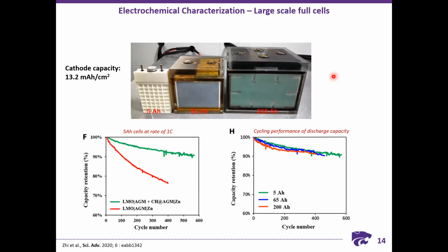They have also gone one more step to produce large scale full cells with the 5Ah, 65Ah, 200Ah batteries for the zinc metal batteries. So for zinc metal batteries, they have used aqueous solution of a combination of zinc sulfate and lithium sulfate electrolyte. So for zinc metal batteries alone, they have made large scale full cells of these capacities. So even when they move to commercial level scales, you can see the capacity retention they were able to achieve at 1C rate for 5 ampere cells. They were able to achieve more than 500 cycles, the capacity retention of around 90%. While without the use of interlayer, we see a steady decline in capacity with the number of cycles.